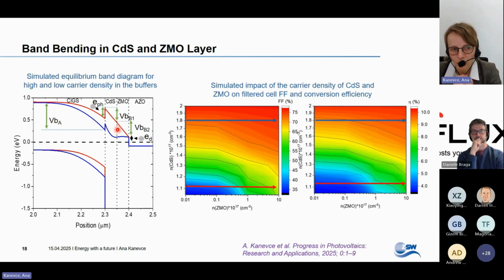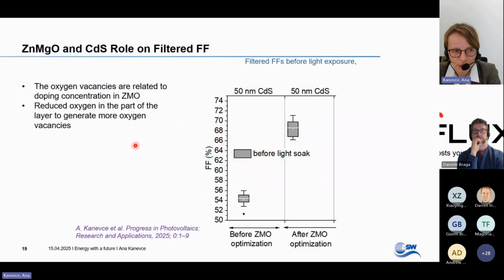Okay, so now we have to dope the zinc magnesium oxide layer. How does one do it? One asks the chemists, and they say it's the oxygen vacancies which are related to the doping concentration in zinc magnesium oxide. So how does one create more vacancies? One reduces the oxygen in part of the layer to generate more oxygen vacancies. So here are the results. Before the zinc magnesium oxide optimization, we had low fill factors, and afterwards we had significantly improved fill factors.